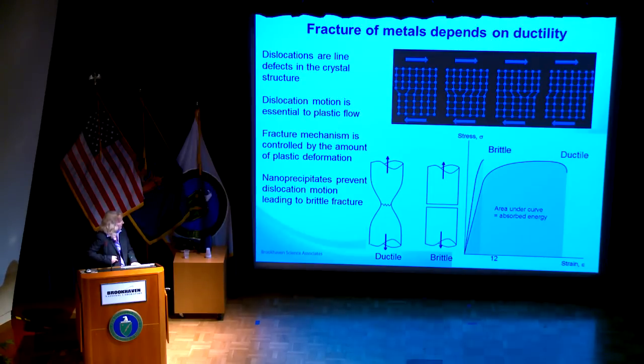This type of deformation can also occur in front of a crack tip, blunting the crack tip. In ductile fracture, this is a stress-strain curve, and you can see how much more energy, the area under the curve is the absorbed energy. So for ductile fracture, you absorb a lot more energy before you fail. Now, if these dislocations can't move for some reason, say a large nanoprecipitate prevents the movement of the dislocation, the material can fail in a brittle way. In this case, it just snaps. We absorb much less energy, and the failure happens much more quickly, so the material is just less tough. This phenomenon also happens at low temperature, where the dislocation motion is also impeded. So it can be impeded by low temperature or nanoprecipitates blocking dislocation motion.